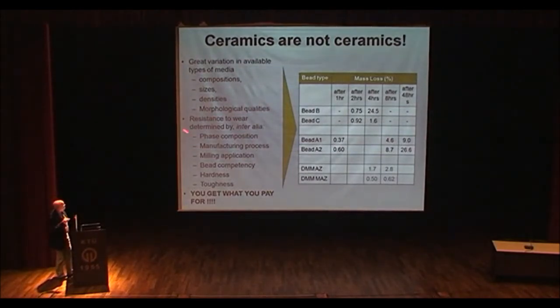One of the factors here we mentioned in phase composition: if the bead is properly made with zirconia, this tetragonal zirconia polycrystal toughening, you actually get a work hardening. The bead gets harder. Strangely enough, it actually work hardens. So after 48 hours you actually get almost zero mass loss. Those are the sort of things you're looking for.